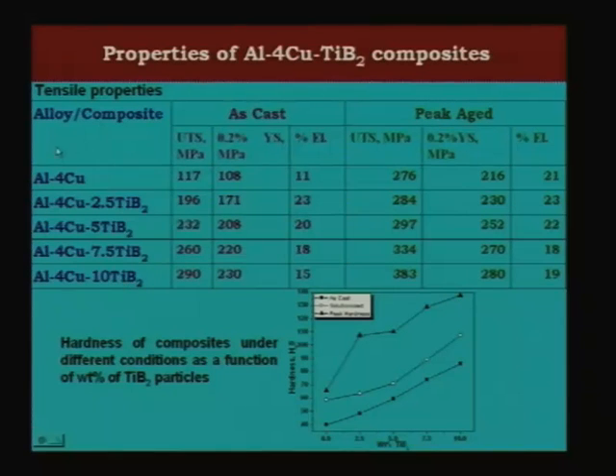If you take the same aluminum copper, if you add silicon carbide, the strength may increase, but the ductility will never increase. In fact, the ductility will fall. This is what happens with the TiB2 particles, because the TiB2 particles are also compatible with the matrix, that you have a good compatibility at the interface, and there are no reaction products at the interface. Because it's happening for the simple aluminum copper also, as cast also, you can see about almost 4% or so.